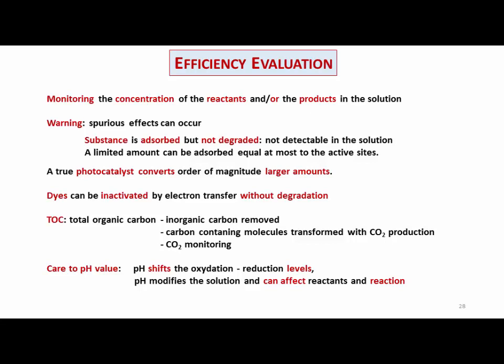Reaction rate, chemically speaking, is just what happens on the surface. It's not the total reaction, which also involves moving things, desorption, and so on. So normally what happens is that most of the time there is a bottleneck that is not the reaction. And if you are measuring the total, you might be wrong in assuming that your reaction rate is worse than that. You're simply not getting rid of the products fast enough. So here's one key point. People sometimes mix reaction rate with the overall reaction efficiency.